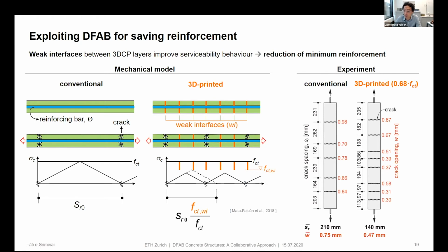So if we put minimum reinforcement to control cracking, if we have weak interfaces, we could even reduce the amount of minimum reinforcement. Because when we do conventional reinforced concrete design, we don't take into account the tensile strength of concrete, or if we have tension. If we have shear, it will be interesting to see what is the effect of the weak interfaces. But if we have only direct tension, we should not be that concerned from the mechanical point of view.